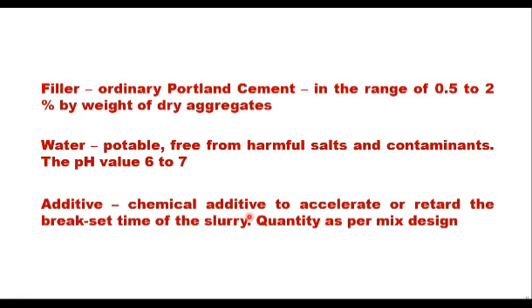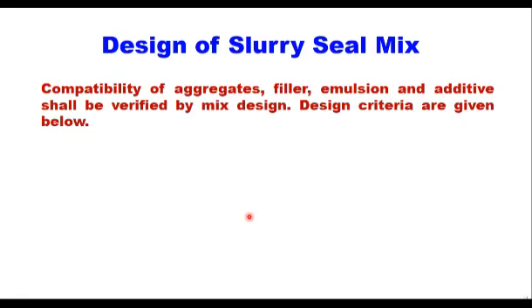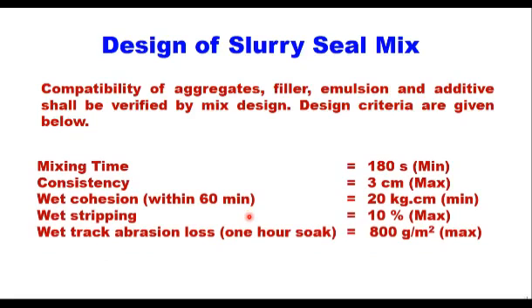Additive and emulsion should be compatible with each other. The slurry mix design basically means checking compatibility of aggregate, filler, emulsion and additive, verified through a mix design process. The design criteria given in IRC SP 78 are: mixing time minimum 180 seconds, consistency not more than 3 cm, wet cohesion within 60 minutes should be 20 kg·cm, wet stripping value maximum 10% (coating minimum 90%), and wet track abrasion loss in one hour of soaking should be maximum 800 grams per metre square.